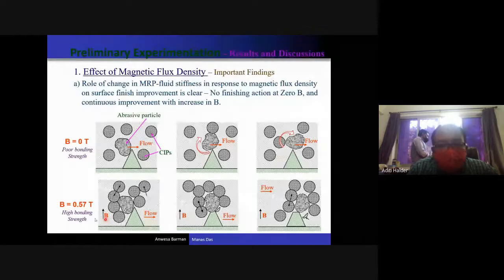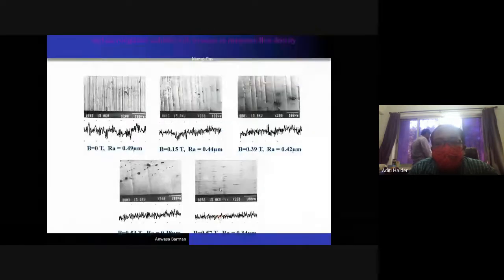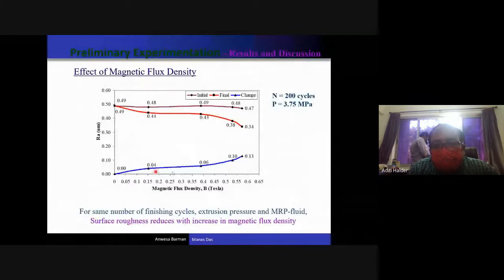Now at higher magnetic field, the CIP particles are bonded together, so the abrasive particles are held in between the strong bonding force of the CIP particles. Whenever they come in front of the roughness peaks, they remove the surface peaks from the workpiece surface, and a small amount of chips are generated. So you can see here that with increasing magnetic field, the change in surface roughness also increases.